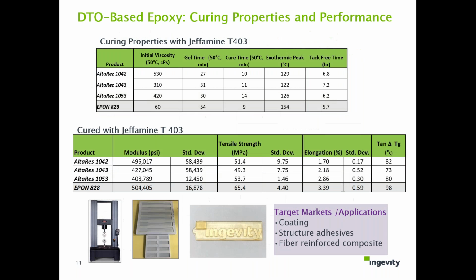This slide starts showing the cure properties. The first curing agent we use is the polyetheramine Jeffamine T403 from Huntsman. This first table shows the initial viscosity, like I mentioned before, somewhere around 300 to 500. And for gel time, we're using EPON 828 traditional epoxy as a benchmark to compare how our DTO epoxy looks and have some benchmark for comparison purposes. So the gel time is shorter compared to the EPON 828 benchmark, and the cure time is pretty similar.